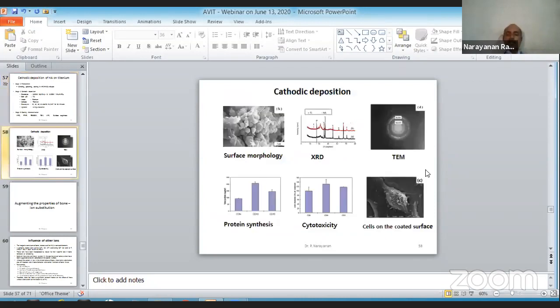The details are available here, and you can see that this is the surface morphology, and the presence of hydroxyapatite is indicated in X-ray diffraction and TEM. And these are the biological studies. You can see that the pristine surface has certain levels of cytotoxicity, whereas the hydroxyapatite coating shows improved cell adhesion and no toxicity. And the coatings also develop proteins in the vicinity, which indicate their surface active state. And when cells are placed near the coated implants, the cells do elongate. This is called a filopodia extension. So the result is that my nano-sized hydroxyapatite coating can be used on implants and placed inside the body.